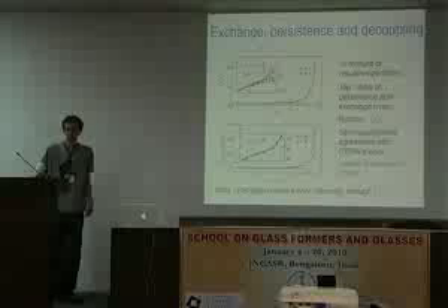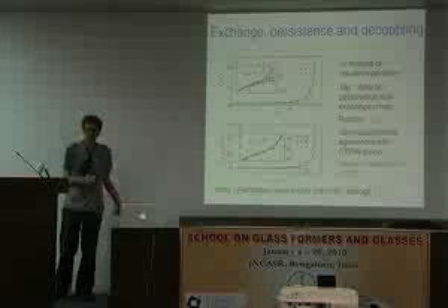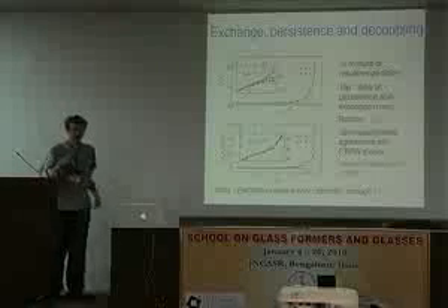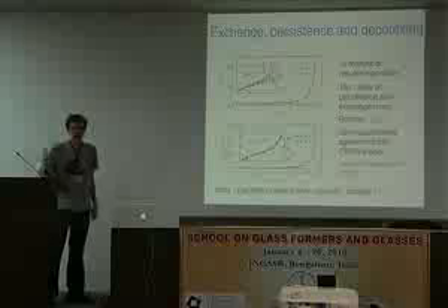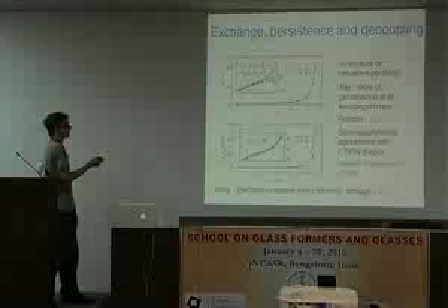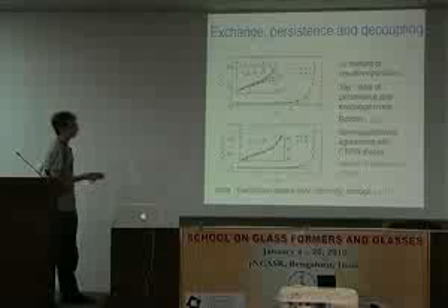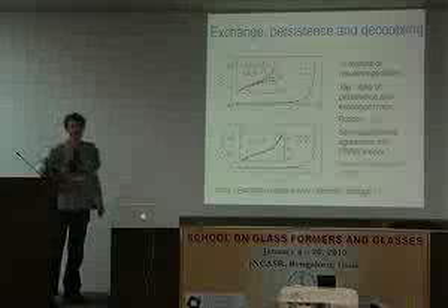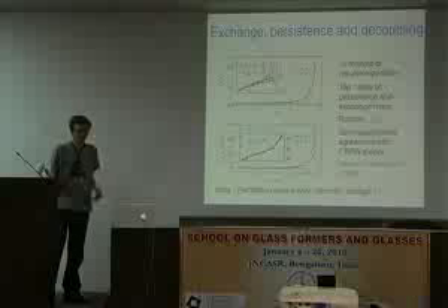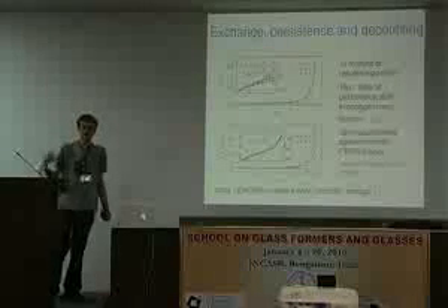And so what's the role of facilitation here? Well, not much directly. Facilitation says that if you've got these excitations in the system and they're sparse, then you'll naturally have a broad distribution of relaxation times contributing to your hopping. So that means that psi of t will be broad. And that means that tau p over tau x is large, and that further means that D tau alpha is large. So there's a question when you look at this data of necessity and sufficiency. So how much do you need to invoke to explain this data? Just really a broad distribution of psi of t. But if you think about KCMs, it's apparent where that broad distribution is coming from, and it doesn't have to be the same mechanism in the real glass.